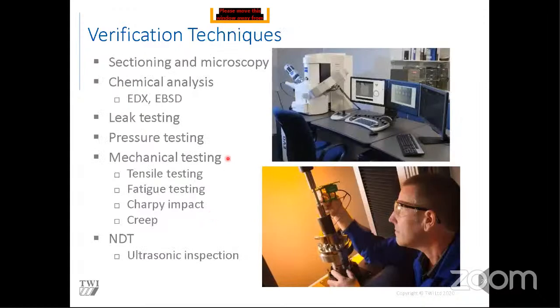Some of the verification techniques we use, the most basic yet the most powerful, is sectioning and microscopy. From this we can see the actual joints themselves, assess the level of porosity if there is any, and see if there are any phases formed, analyzing them using scanning electron microscopy, or the EDX function more specifically. From metallography and microscopy we can get an awful lot of information about our joints.